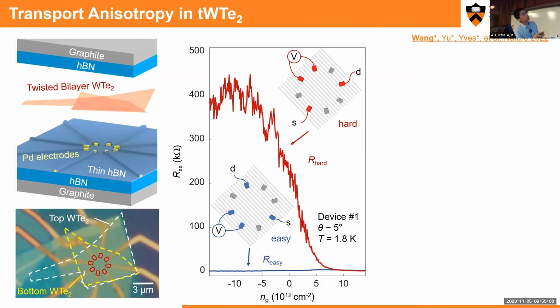The first result shows we measure along different orientations. Actually, we keep changing the contact configuration. We do a rotation, and this is the selected result, which I show to demonstrate the distinct difference along two orthogonal orientations. It didn't show very clearly for the stripe which I plot here, but the stripe on this plot goes this way, and the stripe in this plot also goes this way. Which means that when we send the current along this direction, it shows dramatically high resistance, and when we send the current along the orthogonal orientation, it shows a very low resistance.